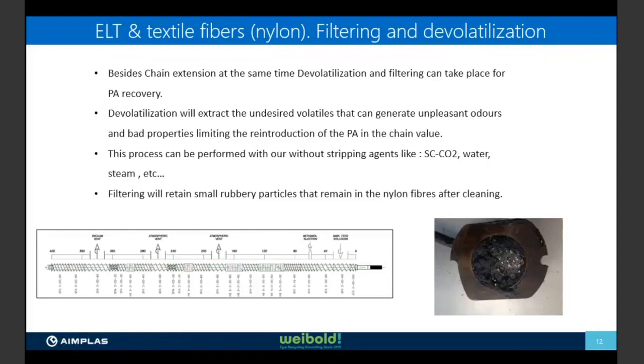Okay, but at the same time that we are doing that, as I mentioned before, we can also filter the polyamide in order to retain the small rubbery particles that can be in this kind of net of textile that comes from the recycling and from the grounding. The technologies for filtering are very advanced in extrusion, so we don't have to go further. It is possible to have automatic screen changers where you obtain very important filtering ratios. And the quality of the material can be also interesting. Here, I didn't put it, but at the same time, or prior to that, we can do a cleaning in a bath. If we clean in a bath, we can also separate by density, and we can remove a lot of particles. So we will improve even more the quality of the polyamides that we are going to recycle.